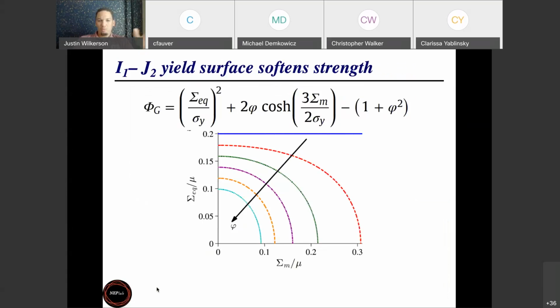Okay. One other thing that we have to account for in ductile metals that's not as important in brittle materials. In ductile metals, as we grow this porosity, yes, the porosity degrades the elastic constants, and we want to account for that, but that's not the most important thing. The most important thing is that the porosity degrades the strength of the material. As I have this porosity in there, it just makes it easier to deform the material plastically, regardless of the stress state. The ease with which it's able to deform, or the resistance to inelastic deformation, depends on the particular stress state.